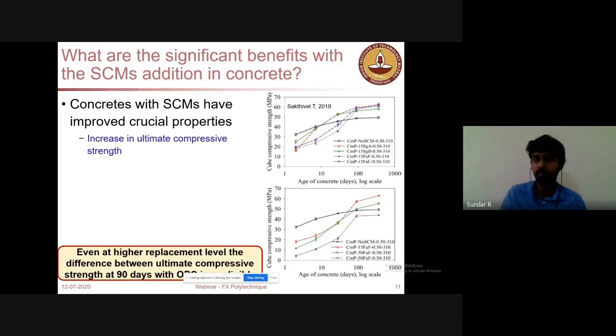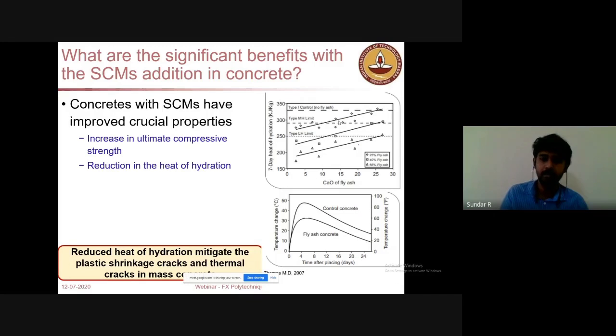So you should know that when you use cement with fly ash or slag, it reduces a lot of heat of hydration. A lot of heat is generated as an exothermic process during hydration in concreting. That could be reduced when you use SCM. So for a massive structure like a dam, if you use concrete with fly ash or slag, you will generate less heat.